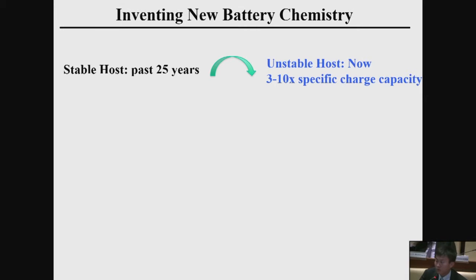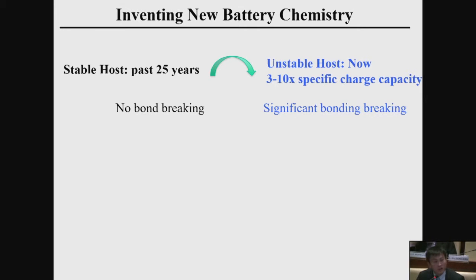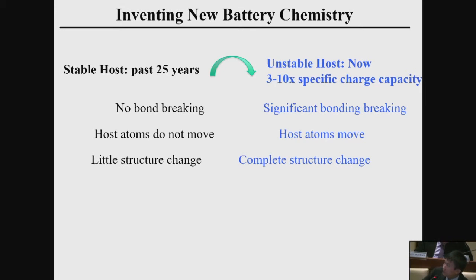They start to come in and do really bad things. The first thing is chemical bond breaking. The host materials holding so many lithium ions, they cannot take it. Their chemical bonds are broken. And the second thing is host atoms move to very long distance. And the next one, complete structure change, big volume expansion. Existing battery material is less than 10% volume change in the materials level. But for the new materials, store a lot of lithium, they have 100% or more volume change. Volume change is too big, the batteries are not stable.